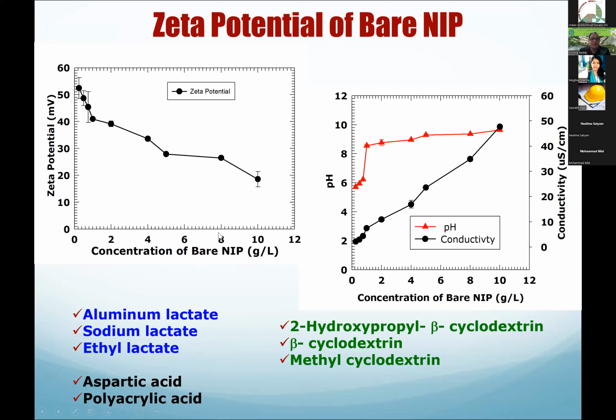Okay, so we know that these bare nano iron particles, we cannot use it. So we need to make sure we add something such as sodium hexametaphosphate. So not exactly that one, but here we are using this aluminum lactate, sodium lactate, ethyl lactate as dispersants. And then we looked at two acids, aspartic acid and polyacrylic acid as a dispersant. And then we use these three types of cyclodextrins based on a lot of literature review and looking at their properties of this. Nobody has actually done any testing with the nano iron particles with these kind of dispersants.